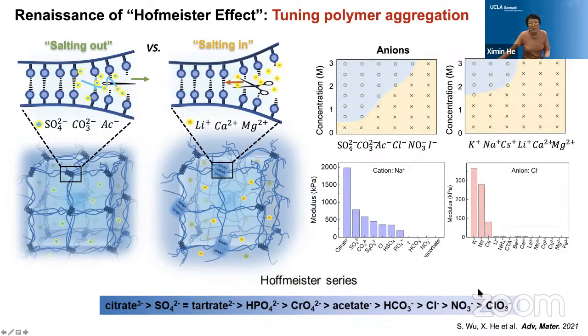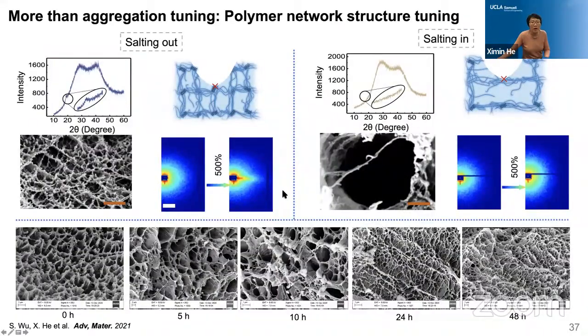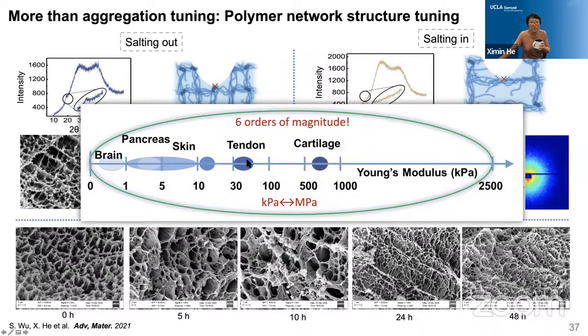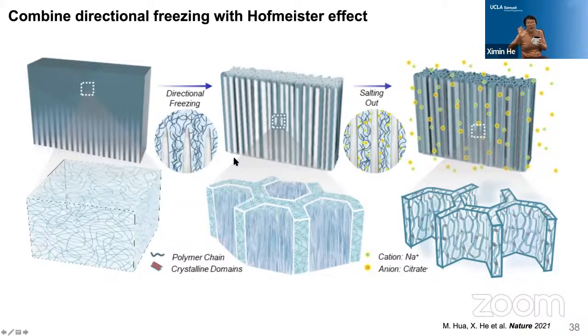On the other hand, if you choose ions from the other end of this spectrum, this may help produce a loosely crosslinked network through the dissociation of the polymer chain aggregation by introducing the water molecules back onto the polymer chain. So with this very basic chemical phenomenon, we tune the pore structure of the hydrogel by soaking the polymer in the different salt solutions over a couple of days, right? Then the measured mechanical stiffness shows that we are able to tune the stiffness of hydrogels across 6 orders of magnitude, which is even broader than most of the soft tissues found in our body. So with this, we wanted to show how far we can push on the toughness, the higher toughness end.